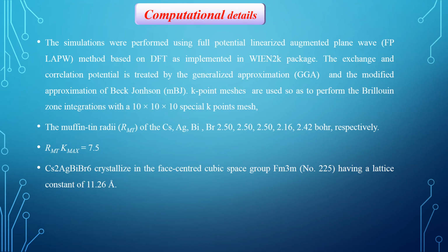The simulations were performed using the full potential linearized augmented plane wave method based on DFT as implemented in the WIEN2k package. The exchange and correlation potential is treated by the generalized gradient approximation and the modified Becke-Johnson approximation. The calculation parameters are as shown.